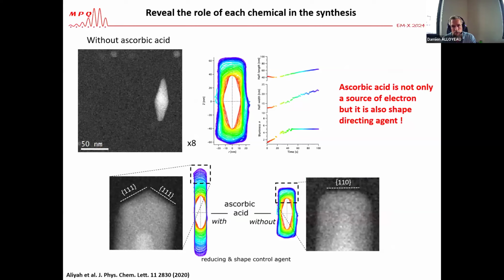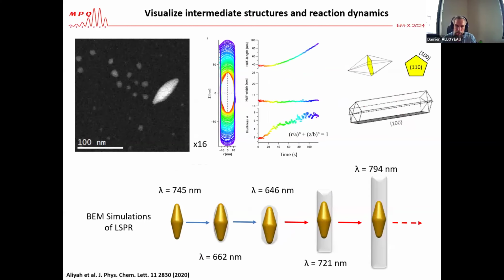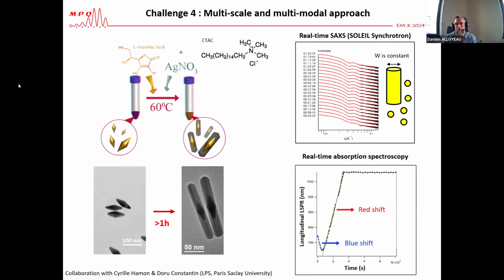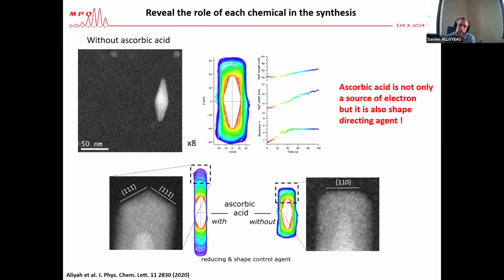Something that was interesting was what was driving the anisotropic growth. If I come back here, you see that many of my colleagues saw that it was due to the CTAC, which is known to stabilize given facets of metallic nanoparticles. But in fact, in this experiment, we have been able to run exactly the same growth experiment, but without the ascorbic acid, which is known to be only the reducing agent. And it turned out that when you remove the ascorbic acid, you start having an isotropic growth, where you have a growth of both the length and the width of your nanoparticles.